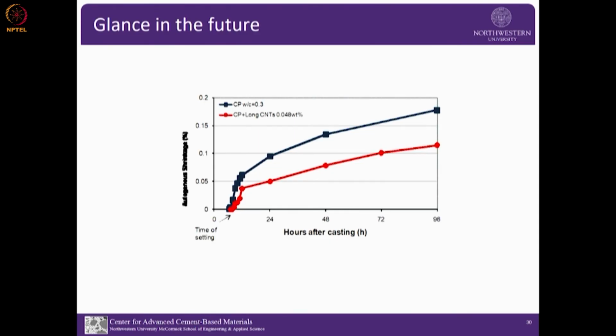So this is a water to cement ratio of 0.3, measured after time of setting. This is the plain cement paste, and this is with a very small amount, 0.048%. So there is a substantial reduction in autogenous shrinkage. And we are still trying to understand why this is so.